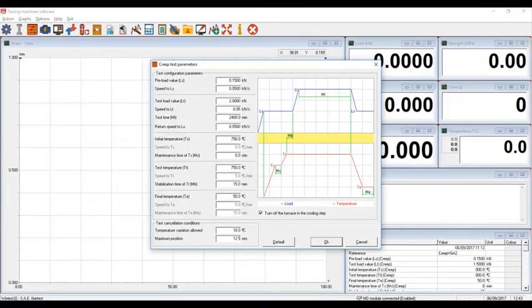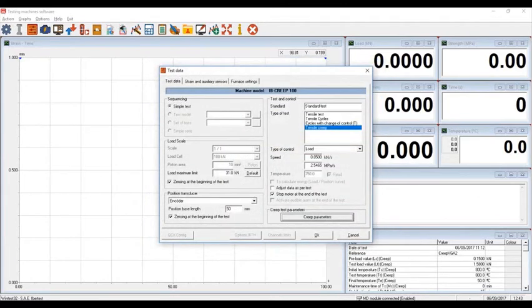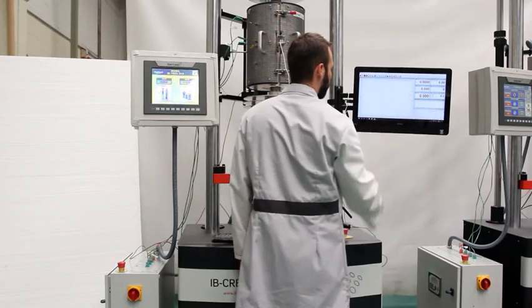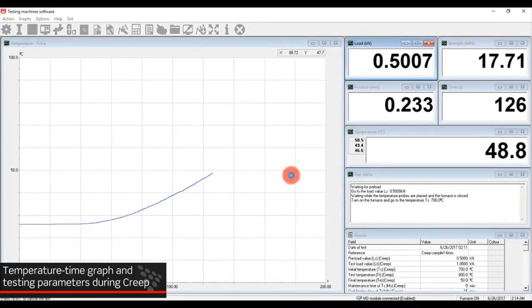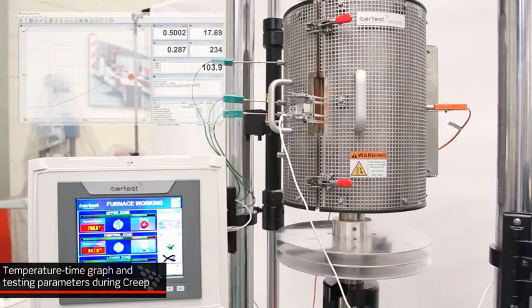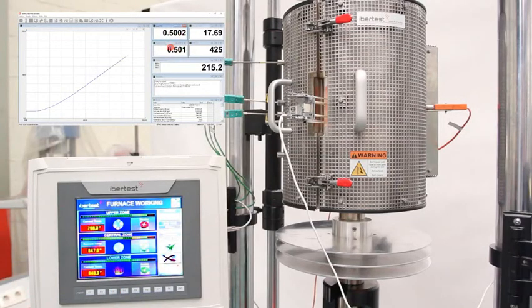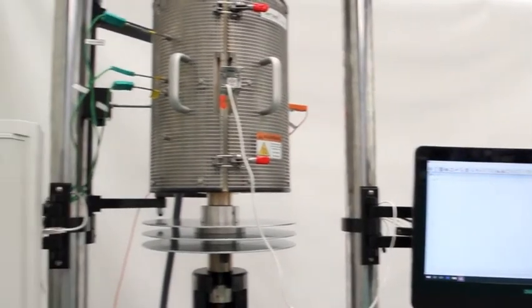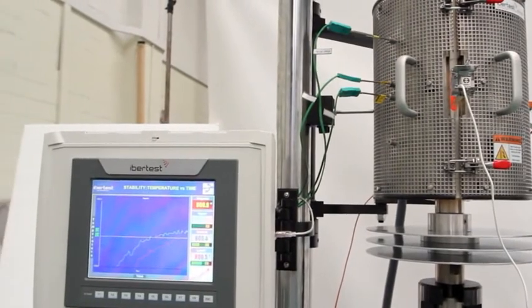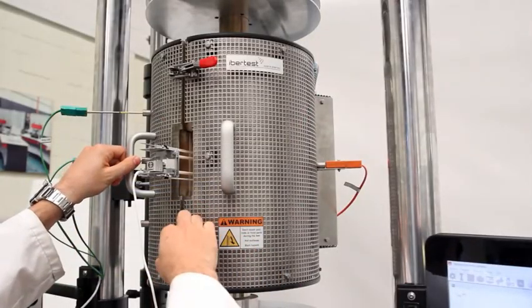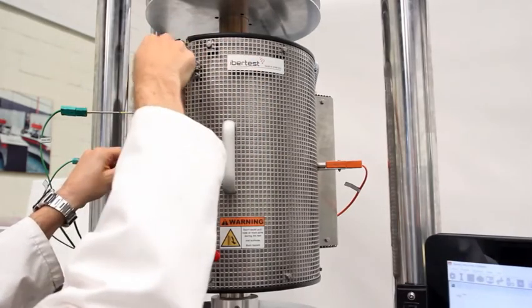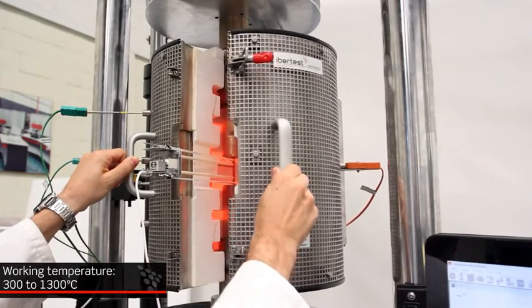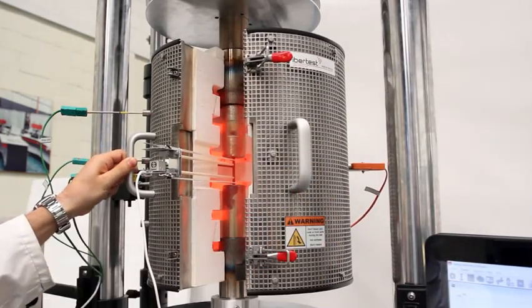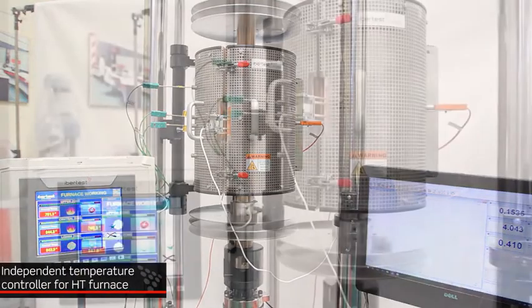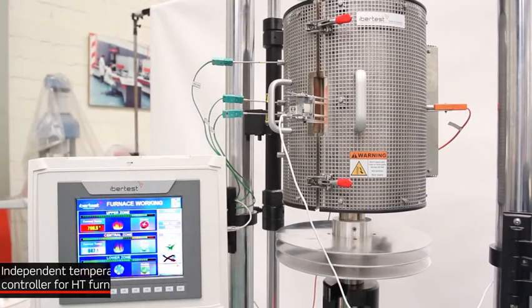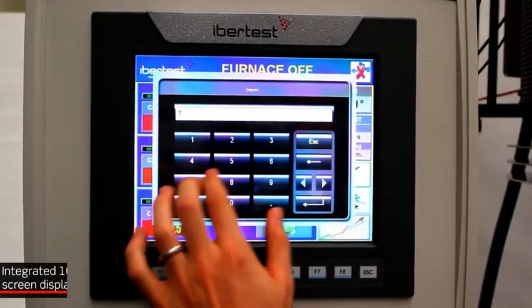So the test is going to be performed at 2 kilonewton, and the temperature is 750 degrees Celsius, and there is the maximum limit load, and there are some safety things. So here you see the temperature shoots up and the force fluctuates somewhere around 0.5 kilonewton. When the temperature shoots up, there will be a thermal expansion, and because of that there might be a force. Because you have applied a force, this actuator will move with thermal expansion, because if the sample is expanding, then there will be a compressive force on the specimen if the actuator doesn't move. So you have applied a preload of 0.15 kilonewton, because of which the actuator will move up.